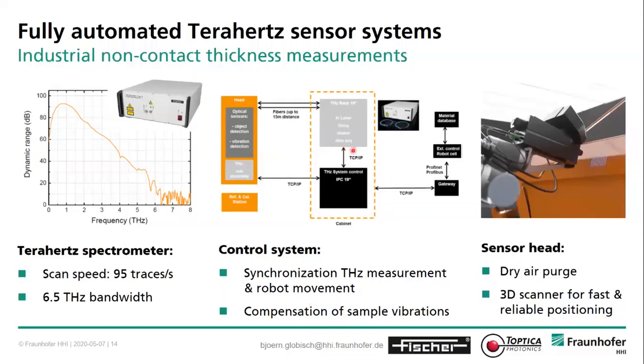Then you have this terahertz spectrometer, which is connected, which is shown here. And then in the end, you have the head that is used for the measurement in reflection geometry. And this also has a quite unique feature, which is the dry air purge, which you need for getting really accurate results of thin layers in order to get rid of water vapor absorption. And then we have a 3D scanner that actually scans the position of the sensor head with respect to the car body in order to get fast and reliable positioning of the sensor.